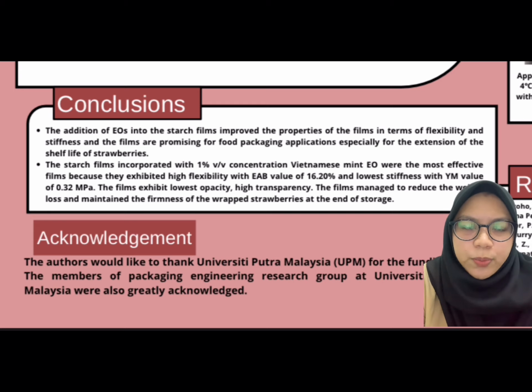The starch film incorporated with 1% concentration of Vietnamese mint essential oil was the most effective film because it exhibits high flexibility and lower stiffness. The film exhibits lower opacity and high transparency. The film also managed to reduce the weight loss and maintain the firmness of the wrapped strawberries at the end of the storage.